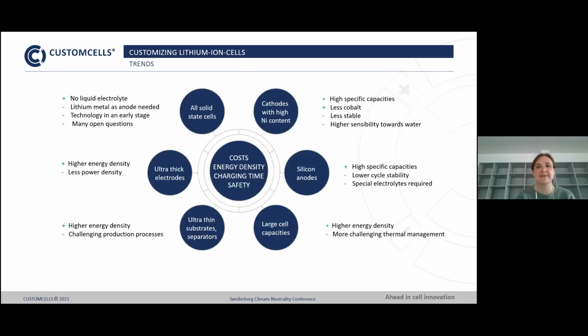So what are the recent trends then in cell development? There are some main foci recently, which are costs, energy density, charging time, and safety. And these main topics are addressed by, for example, cathodes, as I stated, with high nickel content, because of the high specific capacity and less cobalt. However, we have to keep in mind that these materials are less stable and have a higher sensitivity towards water. Silicon on the anode, I also stated that. Here we have to work with a lower cycle stability.